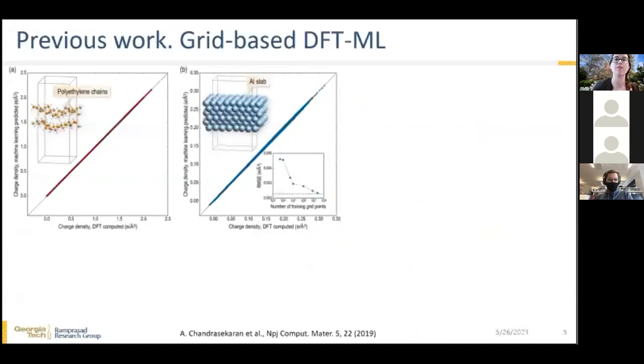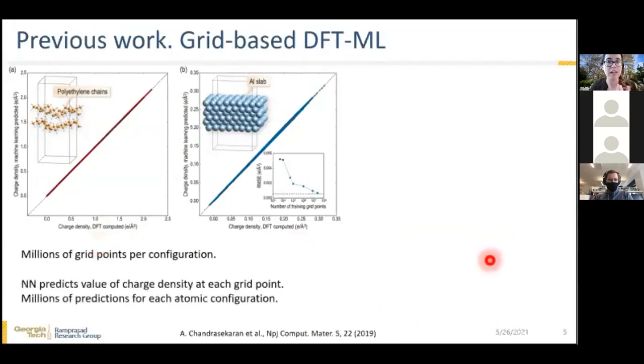So the first successful attempt within our group to predict the electronic structure used a grid-based approach with neural networks. Now, the protocol was applied to two different cases, polyethylene chains and aluminum slab. In the case of the charge density here, the models provided accurate predictions, but they require millions of grid points per configuration. And therefore, it was an expensive endeavor. With the neural network predicting the value at each grid point, each atomic configuration requires millions of predictions to obtain the entire charge density.